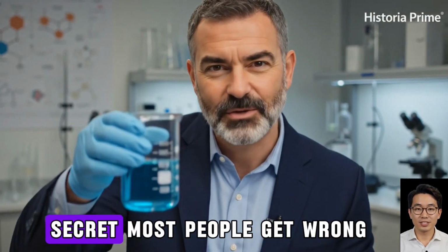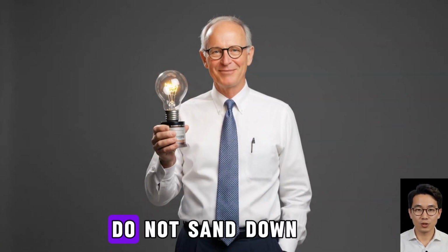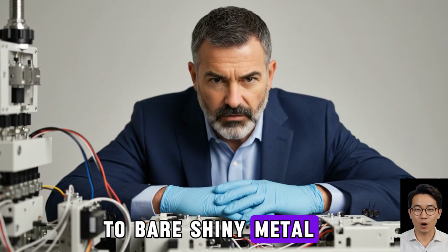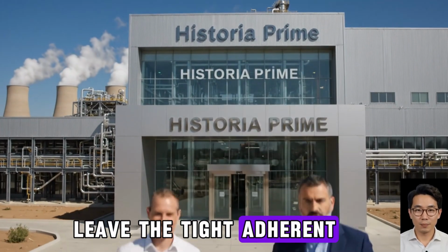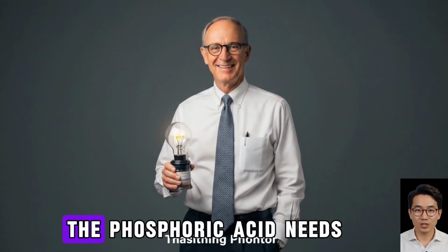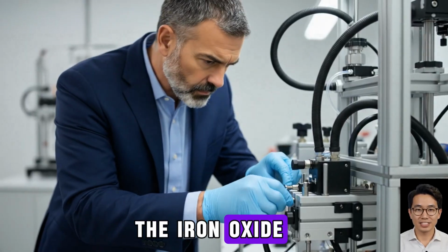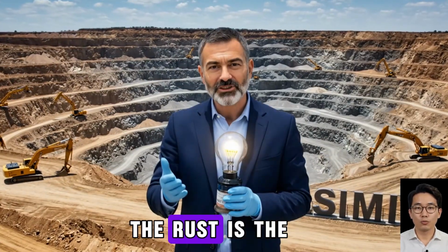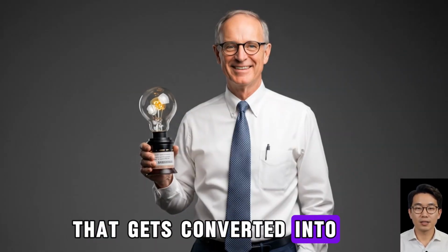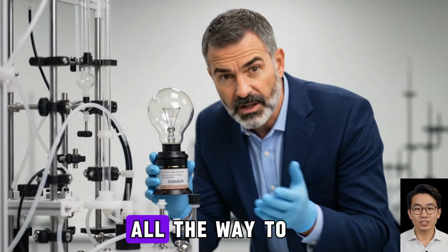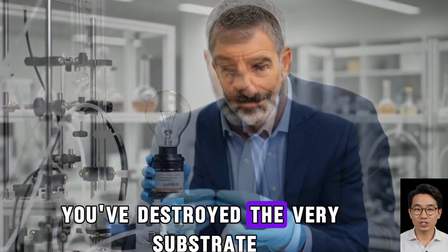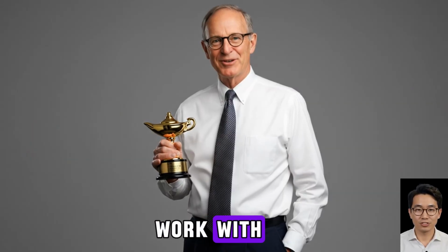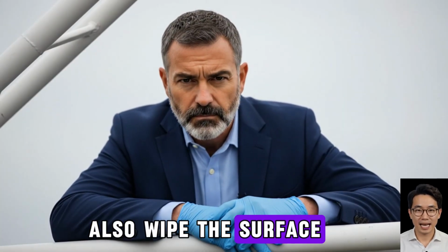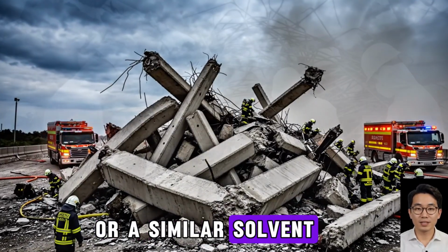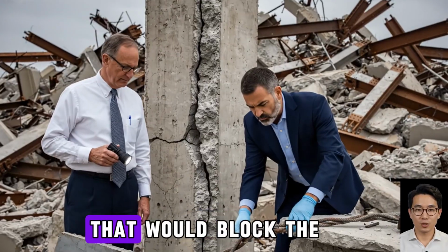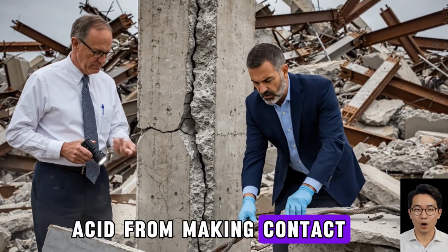But here's the critical secret most people get wrong. Do not sand down to bare, shiny metal. Leave the tight, adherent surface rust intact. The phosphoric acid needs the iron oxide. It feeds on it. The rust is the raw material that gets converted into your armor. If you strip it all the way to bare metal, you've destroyed the very substrate the acid needs to work with. Also, wipe the surface with acetone or a similar solvent to remove any oil or grease that would block the acid from making contact.